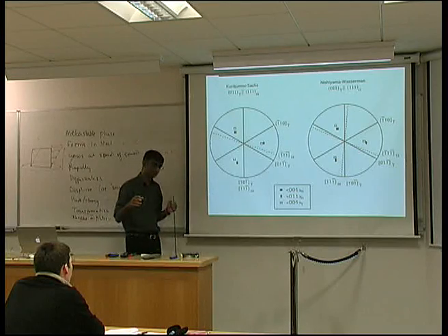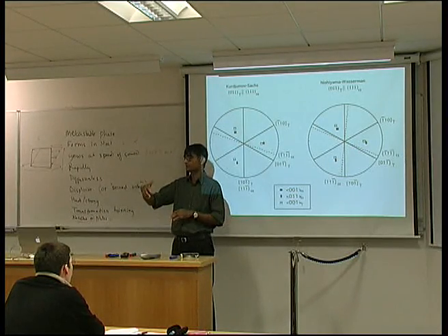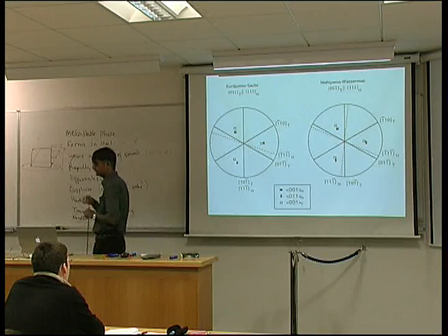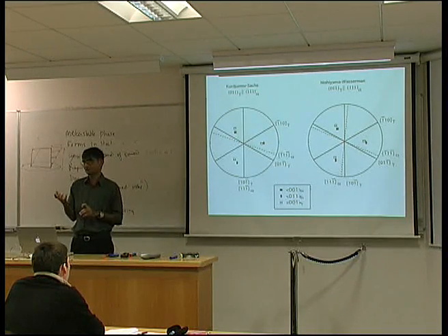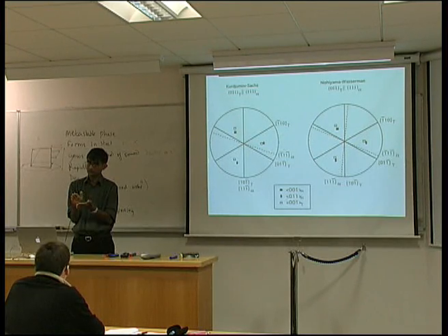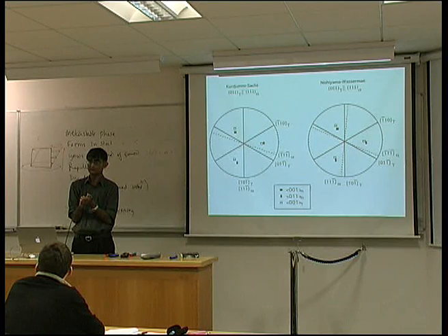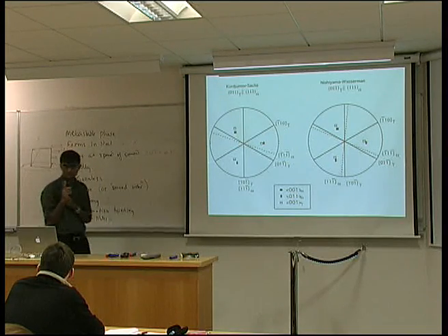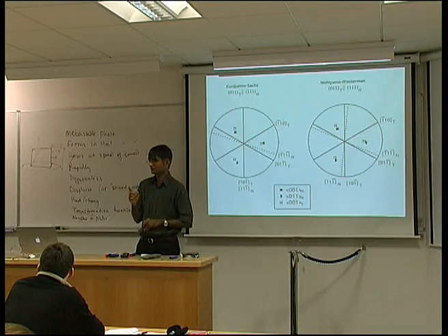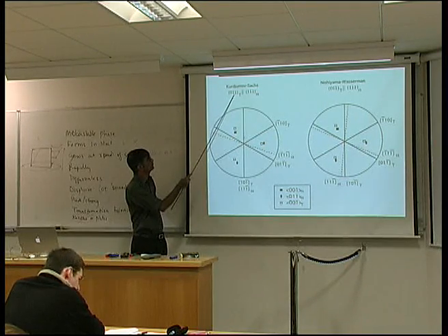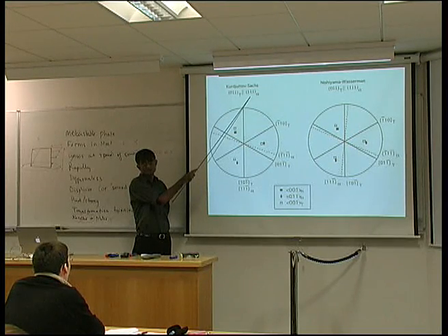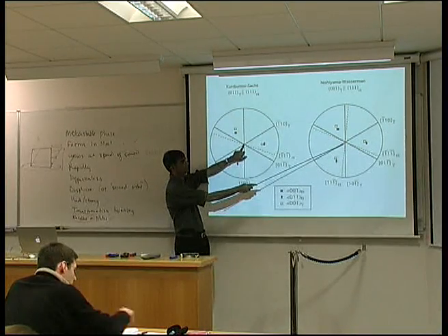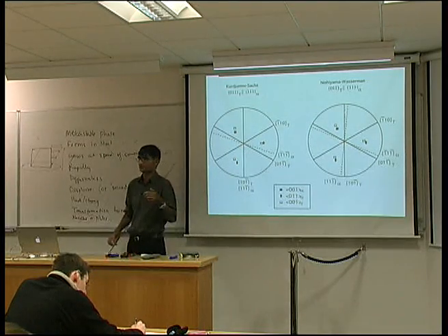Next thing, if you generate one crystal from another by a deformation, then you expect there to be an orientation relationship between the two. That means a reproducible orientation relationship. And for the vast majority of martensitic transformations in all materials, you will tend to have a close-packed plane almost parallel, and a close-packed direction within that plane almost parallel. Not exactly parallel, but almost parallel. So the orientation relationship itself is irrational. Although I have written here that the 0-1-1 plane is parallel to the 1-1-1 plane, that's not an exact orientation. And this is another variant of it, but you can see they are very similar, that the close-packed planes are roughly parallel and close-packed directions in those planes are roughly parallel.